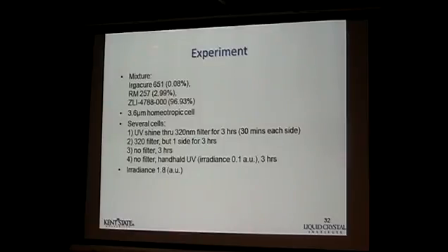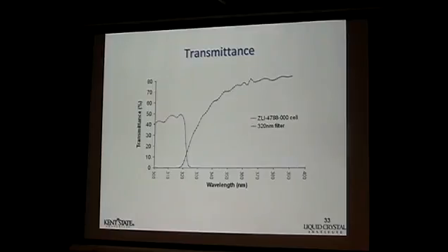Volodymyr. So I think the conditions are like this: you need network forming materials at roughly around 3%, and you need a liquid crystal that has negative dielectric anisotropy. So you need a surface alignment layer with homeotropically aligned material, and you shine a light for phase separation. The interesting thing is to control the kinetics of phase separation. We just mentioned here, you can see that there's phase separation. So we use bandpass filters to filter out most of the light. Anyway, the glass substrate also cuts off a lot of light. It does not allow transmission below 315 nanometers. So there's only a small region of light we can control.